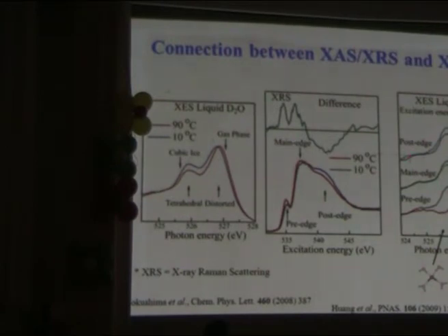We can see if we excite at the post edge here, we excite where we have growing intensity when we cool the liquid, and we get a higher signal of the peak which grows when we cool the liquid. So they are connected. When we excite at the pre-edge, which in the Science paper we assign to uniquely asymmetric hydrogen bond situations, we only get one peak. So we can select which type of local structure in the liquid that we want to measure.